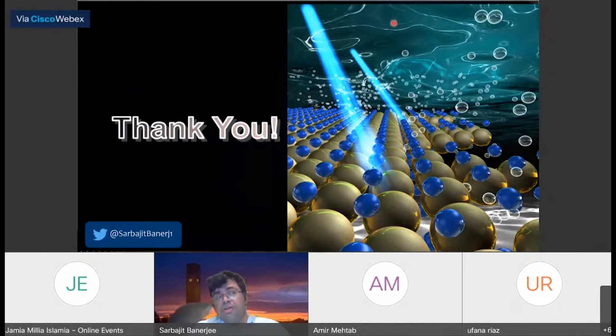Yeah, so commercially, the major challenge for quantum dots has been stability, right? Right now the commercial application of quantum dots is in television screens and such, where they're very well protected. The biggest challenge has been the one we solved in 2018, or really in 2019, which is how do you protect them in water. And so these p-block compounds, by doing ultrafast hole transfer, are how you can make quantum dots viable, or at least viable against photoanodic corrosion. There are other things that also have to play their role.